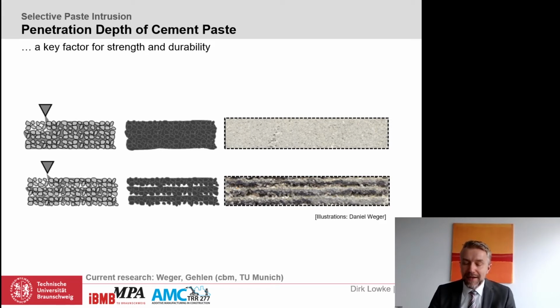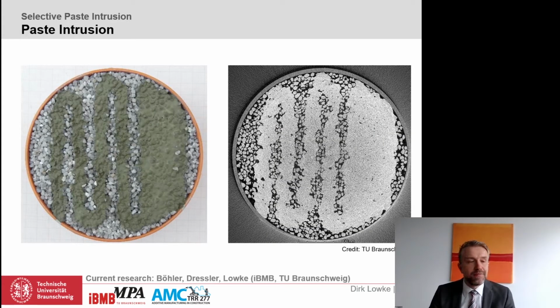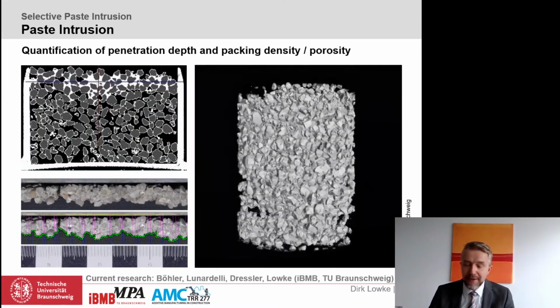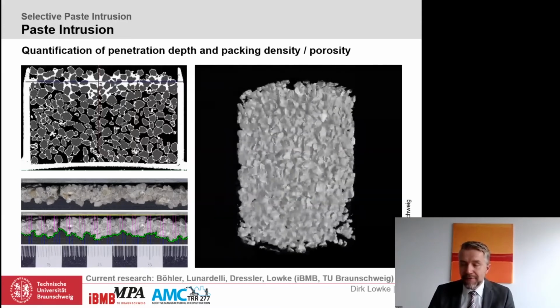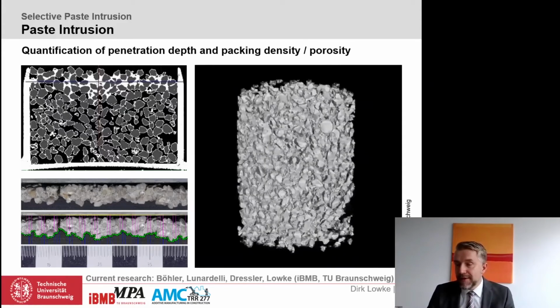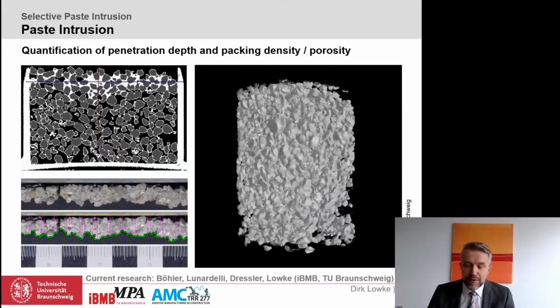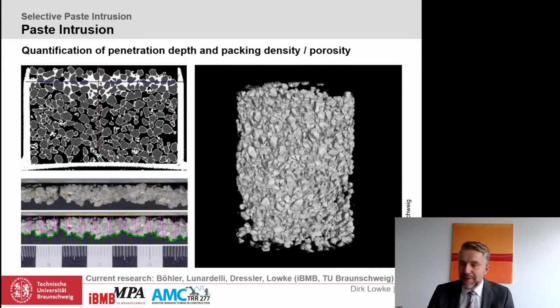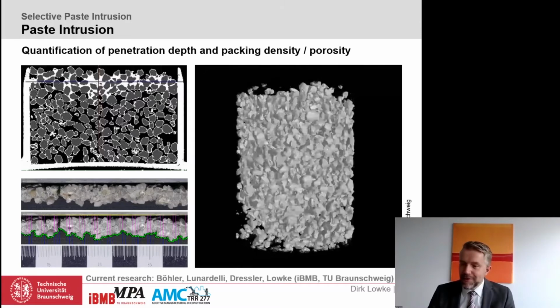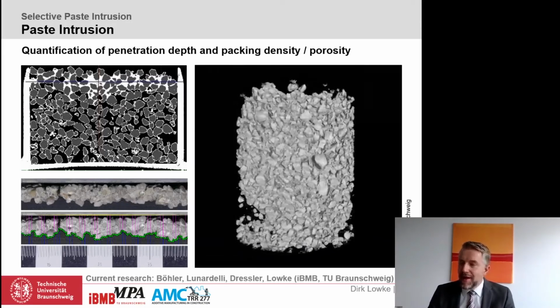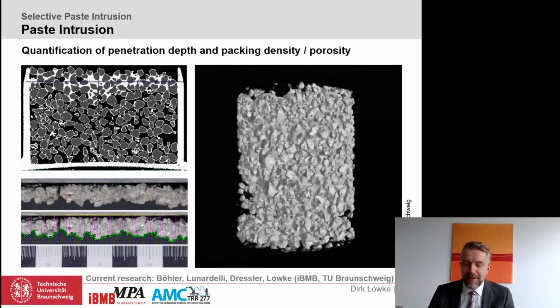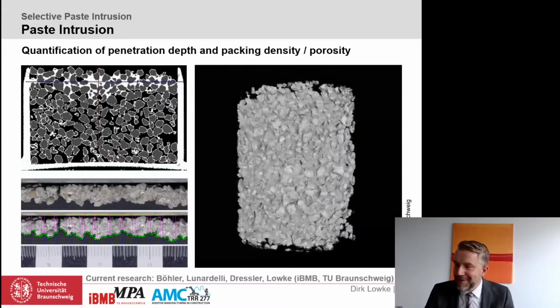It was recently shown by Daniel Weger and co-authors that compressive strength increases with increasing penetration rate. To investigate the penetration behavior of the cement paste, you can perform simple penetration experiments and again use the micro-CT to quantify the results. Here you can see some examples. On the left-hand side, you can see how you can determine the penetration depth of the paste or the mortar. With the aid of computer tomography, we are also able, for instance, to quantify the packing density of our particle bed, as you can see here on the right-hand side. This is also a project which has just started, and the aim here is to numerically simulate the paste intrusion in the particle bed. Hopefully, we will see some results in the coming months.